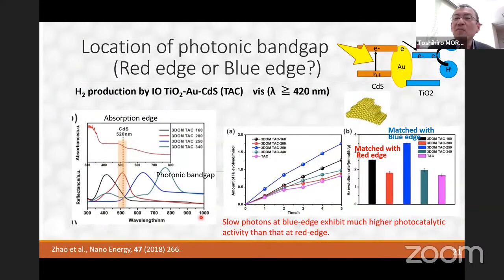Finally, I will introduce one paper written by Zhao et al., published in the journal Nano Energy. This paper reports hydrogen production by inverse opal titania with a three-dimensionally ordered macroporous structure, abbreviated 3DOM, modified by gold and cadmium sulfide under visible light. Okay.